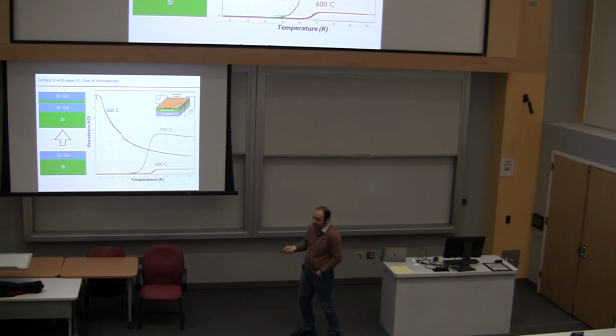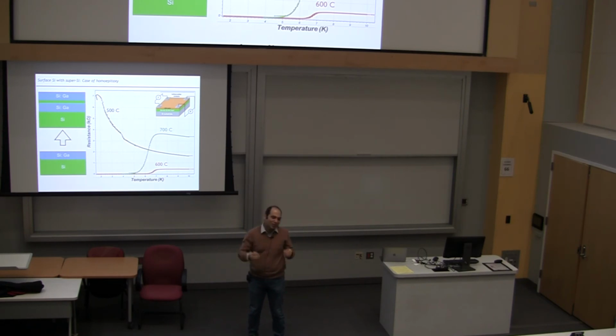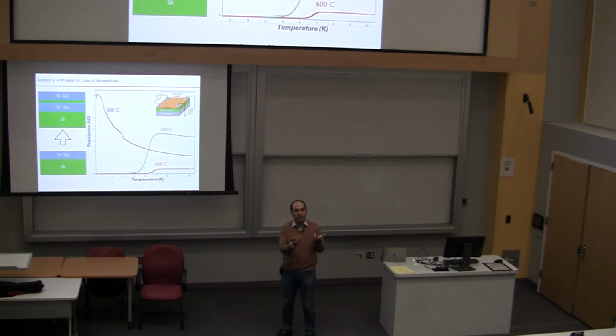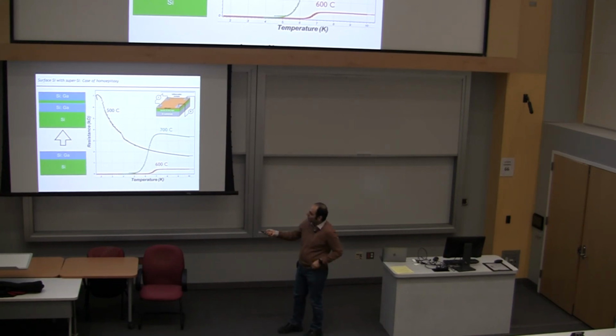The last one is silicon. All of these issues happen because we have different materials growing on different materials, right? So the surface roughness, the mobility, everything. But what if there is a material like silicon that you can make superconducting, and then grow it on silicon, and then you decide not to dope it, it becomes an insulator, and then you dope it to become a superconductor, and then it's homoepitaxy, basically, right? So this is the motivation for this project.